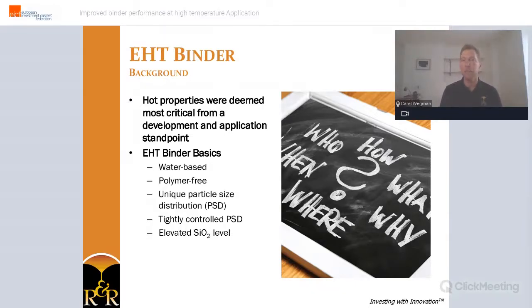The binder developed was given the experimental code of EHT binder, which stands for extra high temperature. It is a water-based polymer-free colloidal silica. One of its primary features is a special controlled particle size, particle distribution, and an elevated SiO2 level.